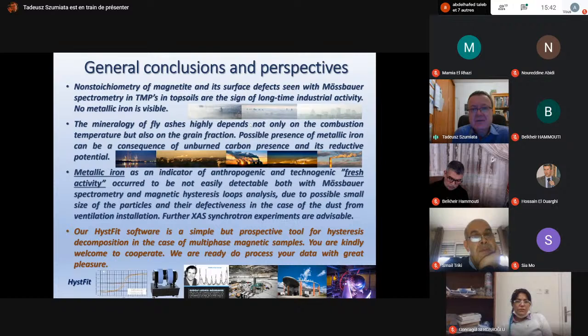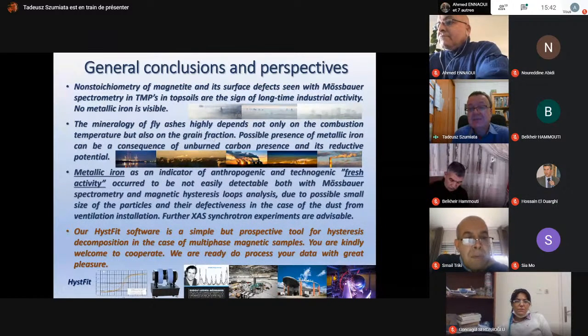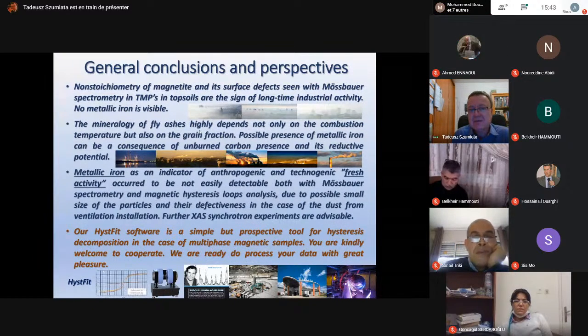And I can formulate the general conclusions: the mineralogy of soils, and for example, non-stoichiometry of magnetite, the contribution of the surface component of magnetite in the spectra, could be a good identifier for technogenical magnetic particles, and could be used for monitoring the influence of industrial emitters on the environment, on the forests, on the fields.